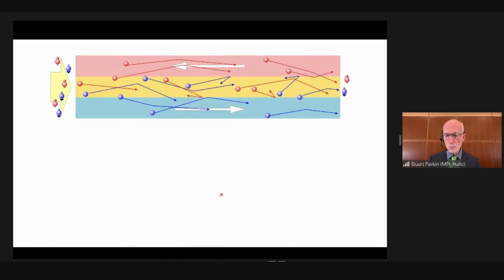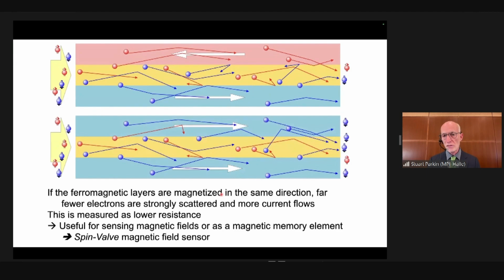Now let's do something very simple. We rotate the magnetic moment direction of the top layer so it's pointing to the right in the same direction as the bottom magnetic layer. Now, in this case, when we introduce current, then the blue electrons are favored in all these layers, and so they can essentially short-circuit the current through this sandwich. And we've created what we called a spin valve. The valve turns on and off current by taking advantage of the spin polarization of the current and its relatively stronger scattering rate for one spin orientation compared to the other.